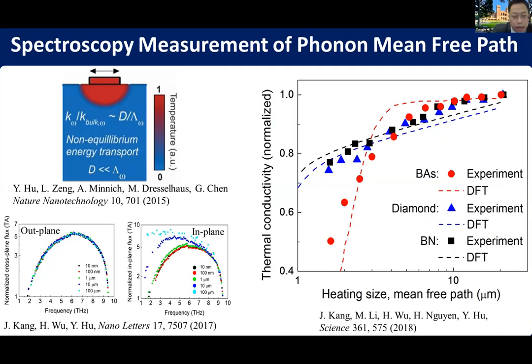So we understood that, as shown in the bottom left figure, we plot out-of-plane and in-plane heat flux during this measurement configuration as a function of different heating size. You can see the out-of-plane heat flux remains the same for different heating size, but in-plane reduces when you reduce the heating size. So that indicates the measurement actually has in-plane suppression of heat flux to probe the ballistic transport.